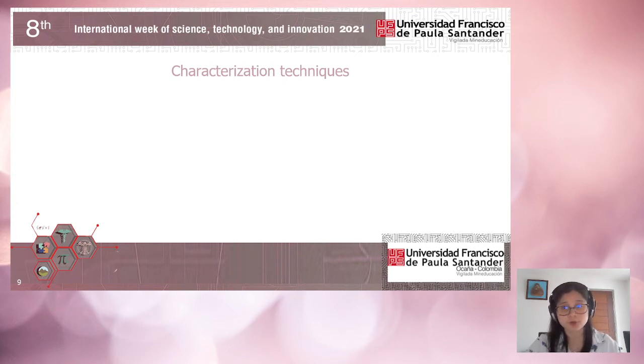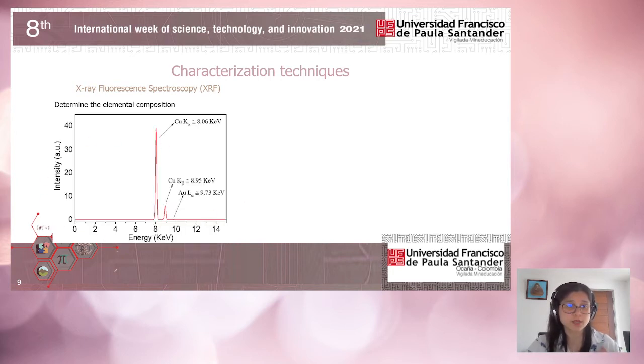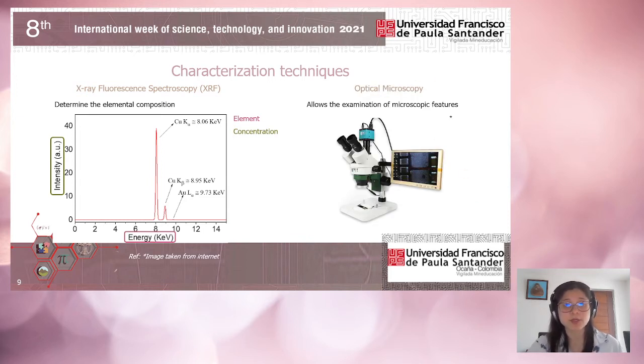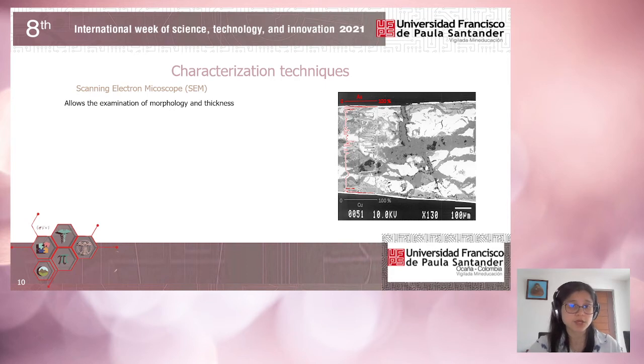The characterization techniques that we used were, first of all, X-ray fluorescence spectroscopy to determine the elemental composition. In the image over here, we can see a typical XRF spectrum. On the x-axis, we can see the energy. The energy of the electrons was measured, and this relates directly to the element that is found in the sample. The intensity of the measurement is directly related to the concentration of this element found in the sample. We also use optical microscopy that allows the examination of microscopic features that were really important for our study. Finally, we use a scanning electron microscope to analyze archaeological objects found in Dos Cabezas sites. This allowed the examination of morphology and the thickness of the gilding.